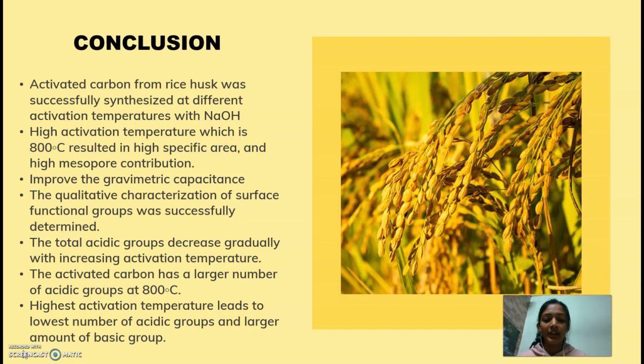Hence, the activated carbon has a larger amount of basic groups at 800 degrees Celsius. It is because higher activation temperature leads to a lower amount of acidic groups and a larger amount of basic groups. So, activated carbon obtained from rice husk by sodium hydroxide activation at 800 degrees Celsius may be a suitable candidate for application as supercapacitor electrode material.